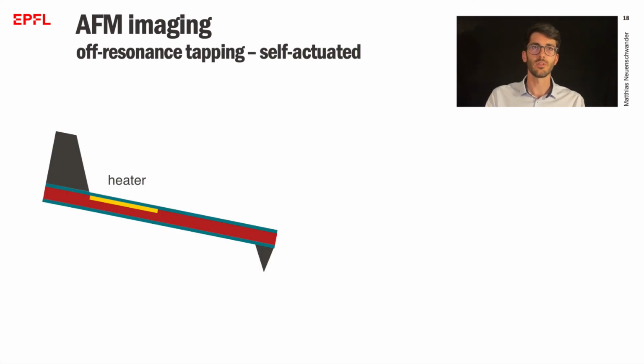So in conventional off-resonance tapping, the sample is actuated below the scanner resonance and thus limited to a few kilohertz. This corresponds to the couple of thousand force curves we can get per second. In our case, we use the integrated actuator of the cantilever to actuate the device rather than the sample. Since the cantilever resonates at much higher frequencies than the scanner, we can operate it much faster, at tens of kilohertz. This allows us to obtain data at more than 10 times faster rates, and thus to get images quicker.